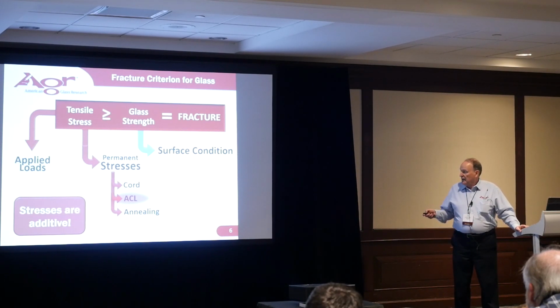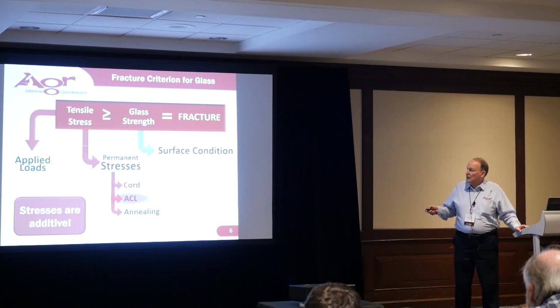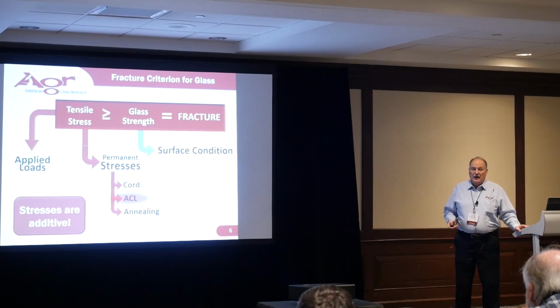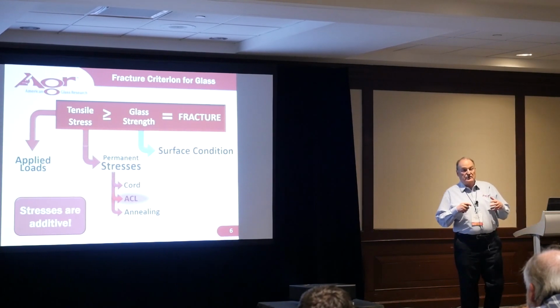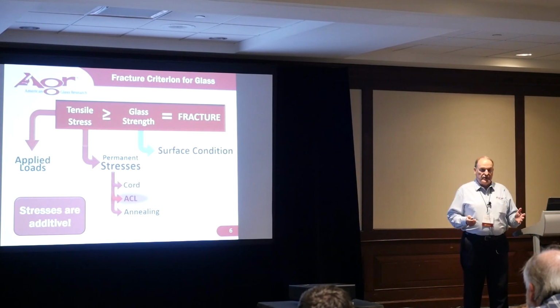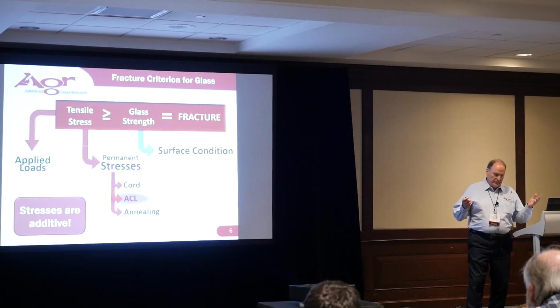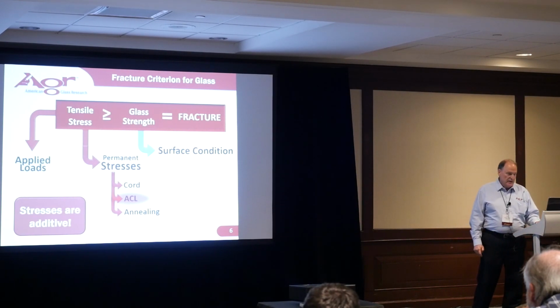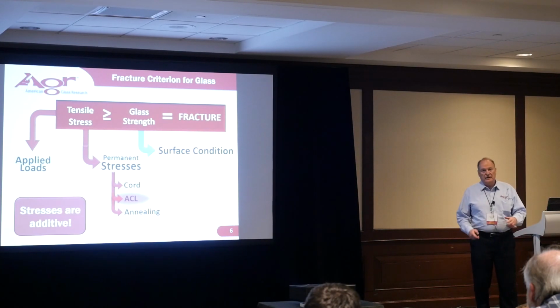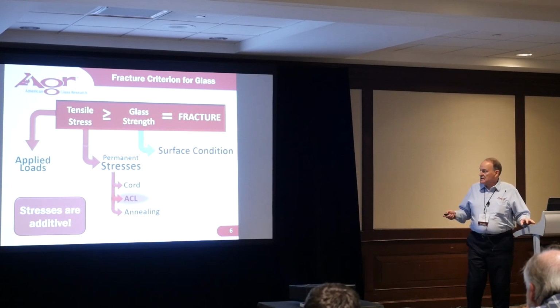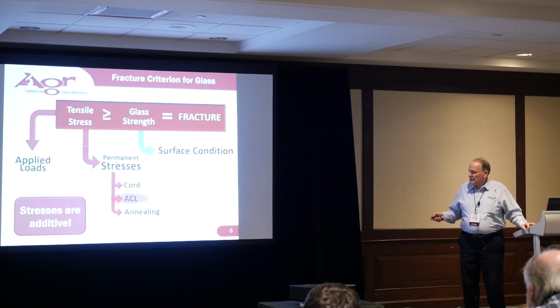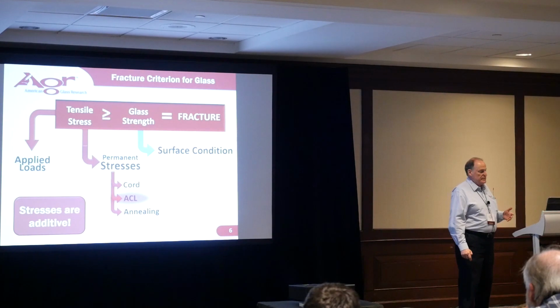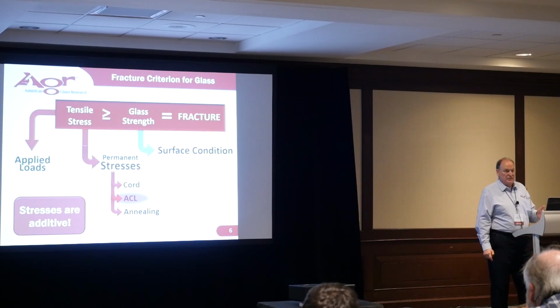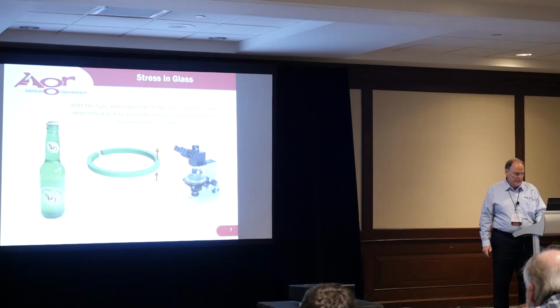And if these are too high, they add directly with the stresses created by these applied loads. That increases the total magnitude of the tensile stress, oftentimes resulting in values that are higher than the expected surface strength, and the bottles will fail. So that's why we were primarily interested in conducting this study, to assess how much stress is actually created by these applied ceramic labels when the coefficient of thermal expansion is different than the glass itself.